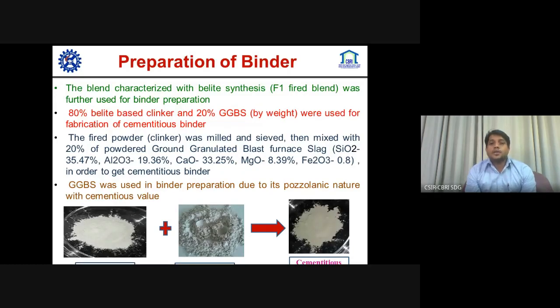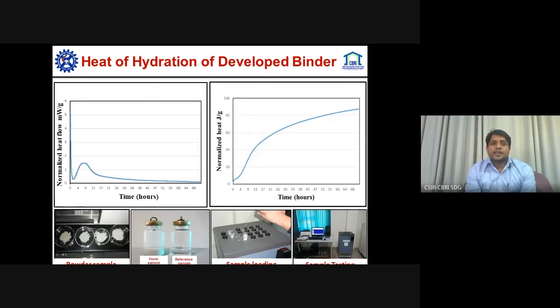The blend characterized with Belite synthesis, which was F1 fired blend with nanosilica and lime sludge, was further used for binder preparation. 80% of Belite based clinker and 20% of GGBS were used for fabrication of cementitious binder. The fired powder was milled and sieved, then mixed with 20% of ground granulated blast furnace slag, GGBS, which has silica and alumina with calcium in their composition. So the GGBS is used in the binder due to its pozzolanic nature, which will provide the cementitious property to the binder. On the heat of hydration analysis of this developed binder, it was clear that it can be compared to the OPC cement.